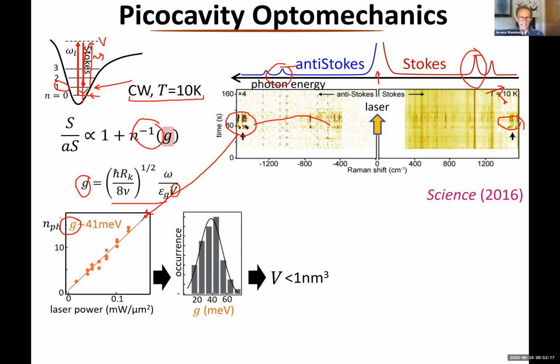So we can make a histogram over many, many different samples, and we can see that these Gs vary around 40 millielectron volts or so. And if we feed that into this formula, we find that the optical volume is much less than we expect. It's now less than a nanometer cubed. So this is what the data tells us.